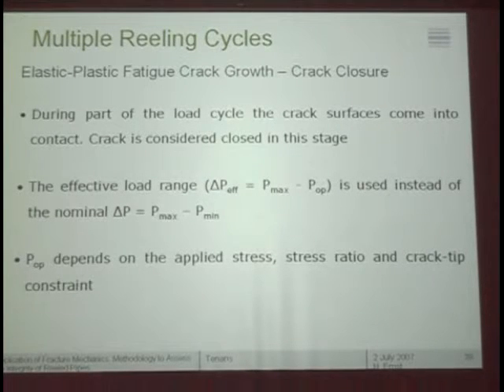We also are using the closure effect that is probably known to everybody. That is, during part of the loading cycle, the crack surface coming into contact, the crack is considered closed in this stage. Of course, there is a difference between opening and closure, but let's simplify it a little bit. Effective load range, delta P effective, is P max minus P opening, and this is what we use instead of the nominal one. And we simply obtain these formulas for the P opening from the literature.